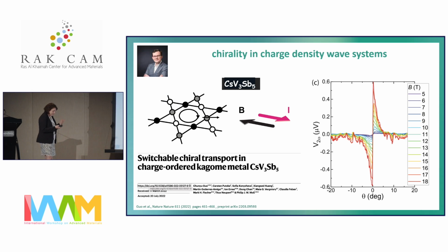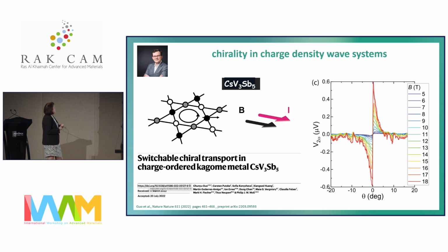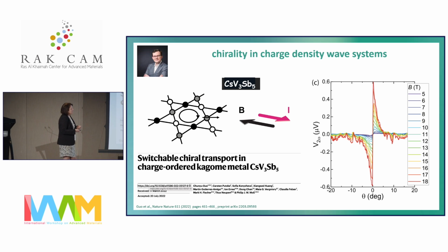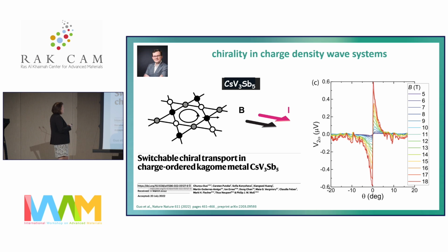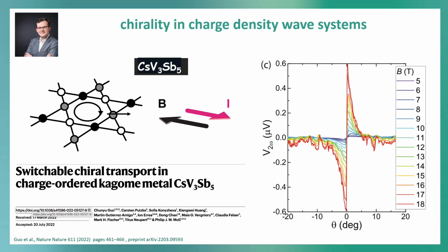So we liked especially this compound because I like chirality, because it turned out that in this compound, and this was work we did with Philip Moll, if we apply a magnetic field, depending on whether we apply it perpendicular or in the direction of the current, we get a chiral current. So we did second order transport measurements. So the magnetoelectric effect, which you normally only see in chiral organic crystals, for example, or in tellurium, we saw a nice large effect under a magnetic field in this compound, which I like, because as a chemist, if I want to do chiral catalysis, if I have a material I can switch from one chirality to the other chirality, this is super cool. Okay, this is for the organic part. This would be a part of my chiral talk.